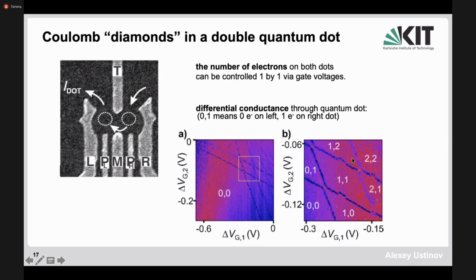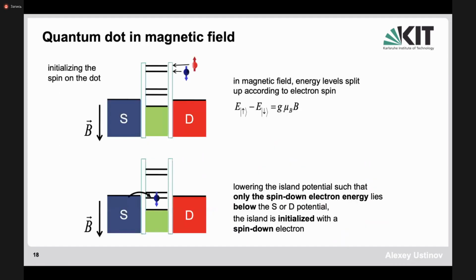Now the most interesting, of course, is this area here. In this area, you see that you have a small joint between the 0, 1 and 1, 0 states. And that's where an electron can tunnel from the left dot to the right dot and back. And if the electron remains coherent, it can actually form a superposition state, like in the double well potential, and this can be manipulated as a qubit, just as an example, of course. So this type of states have been, of course, manipulated. But remember now, the charge states are not coherent.